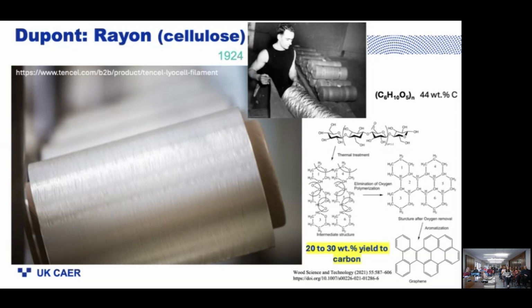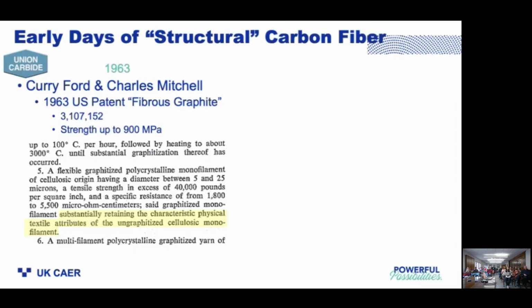It should be pointed out that cellulose has got a lot of oxygen in it. That's not good if you're interested in the carbon yield. Something like 20 to 30% of the weight of the cellulose was converted to carbon. It's kind of low, but nonetheless they were successful in producing a carbon fiber that had pretty good strength for the day, about 900 megapascals.